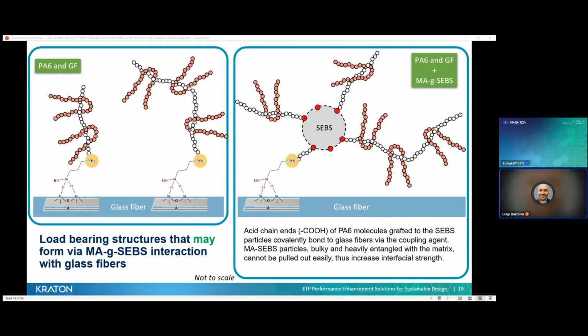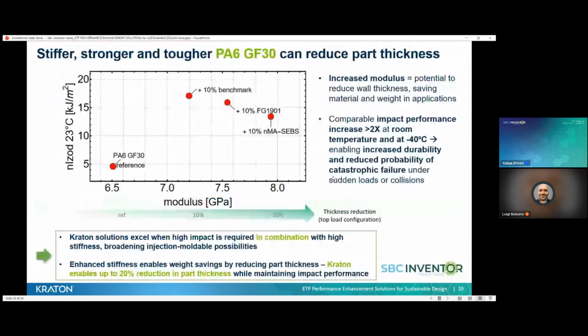Going forward, it is important to realize that only a small fraction of the SEBS particles are needed in this mechanism. The rest remain dispersed in the matrix far away from the glass surface. And in all cases, SEBS preserves its soft characteristics. For this reason, the SEBS particles dispersed in the matrix, next to the improvement in tensile properties, we also see the classic expected increase in the impact resistance of the composite that is related to the deformation mechanism taking place in the matrix rather than at the interface.